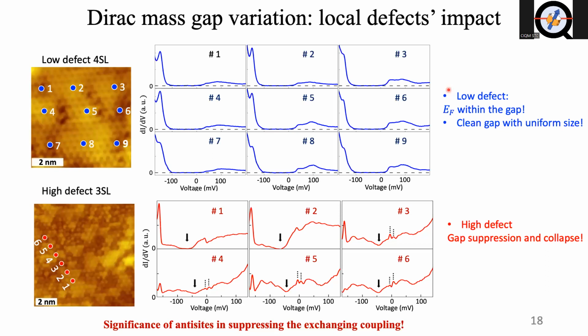Considering that our sample is pretty intrinsic, right? This is because the Fermi level still lives inside the gap. It's pretty much an intrinsic sample. So later on, when we do this model calculation, we think that the N-type dopant and P-type dopant are pretty much compensated with each other. Yeah.